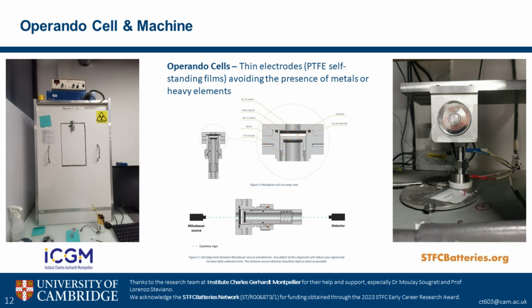So another thing is that to collect a good signal-to-noise ratio with your spectra, you need to be collecting from 2 to 4 hours. So Operando measurements work really well for magnesium, where you're cycling really slowly anyway. If you were wanting to look at slightly faster charging materials, then you could do interval pulses of charging and then relaxation while studying your material.